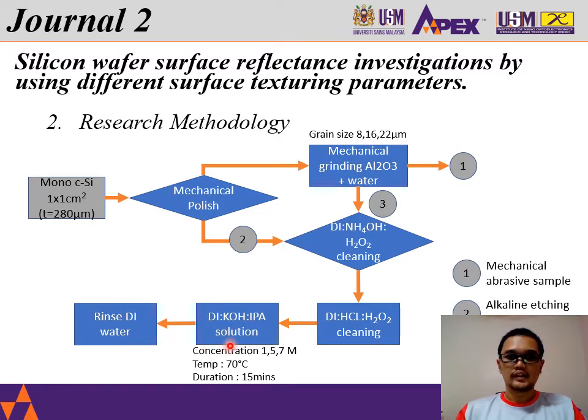Here, three concentrations were evaluated: 1 mole, 5 mole, and 7 mole. The temperature is fixed at 70 degrees Celsius, and the duration is also fixed at 15 minutes. The last step is rinsing with DI water.